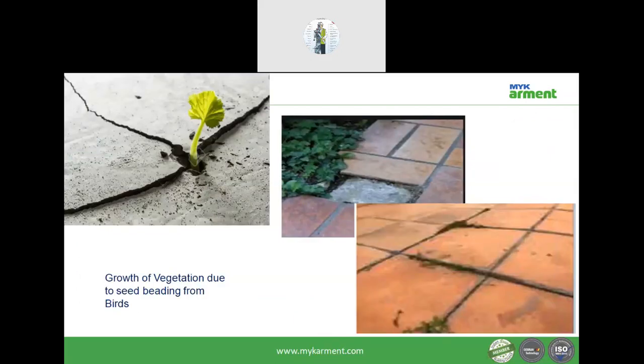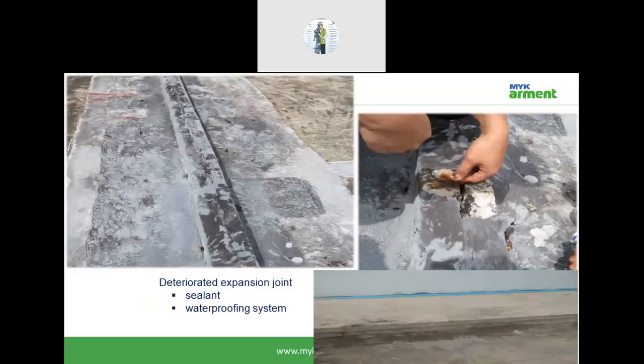Certain times, if the surface is not prepared properly, or if no maintenance is done properly, then because of birds, they drop some seeds and plants grow up on your terrace. When their roots try to penetrate, there is a high chance of a crack developing. And this is another problem, because most of the time we see deteriorated expansion joints. Some people use some kind of sealant at the joints without any protection, then apply some cementitious coating on top, and after due course of time they disintegrate and peel off from the surface.